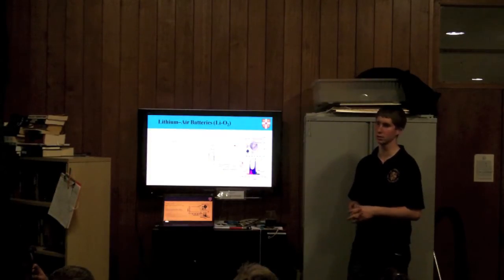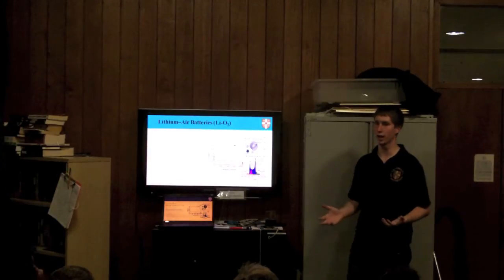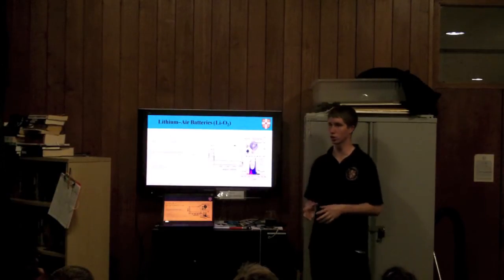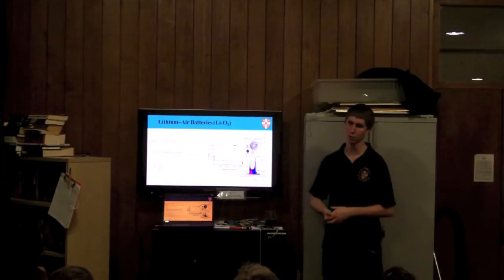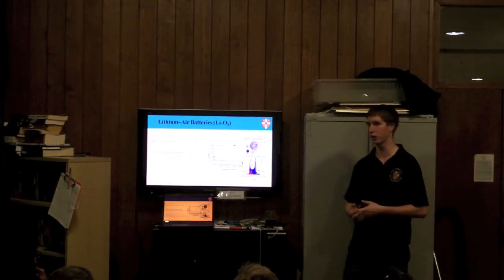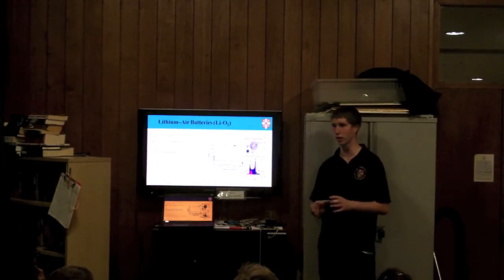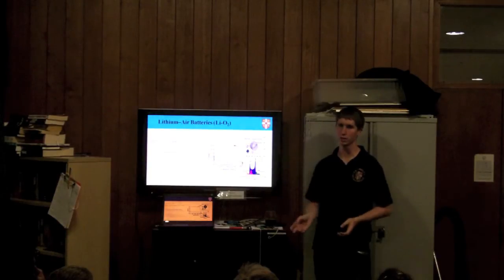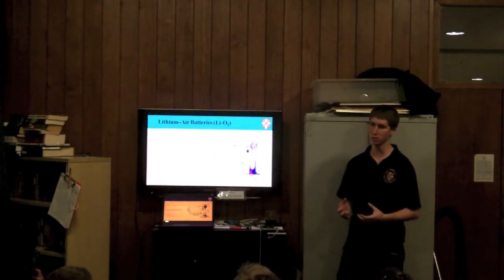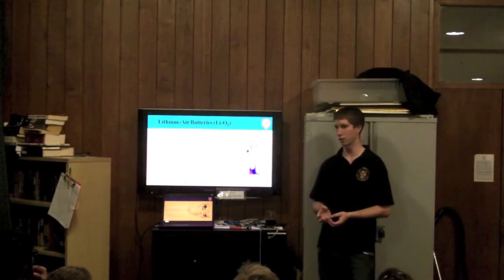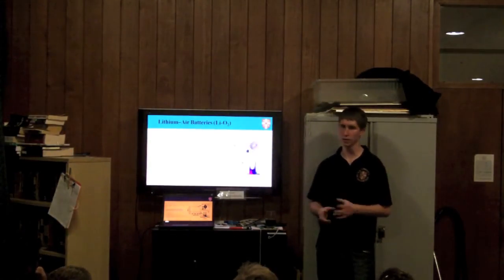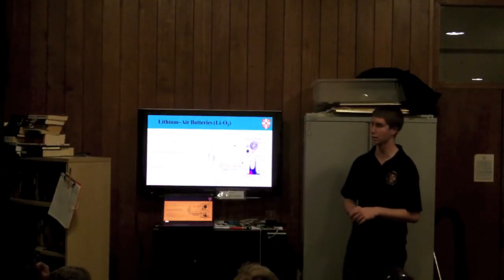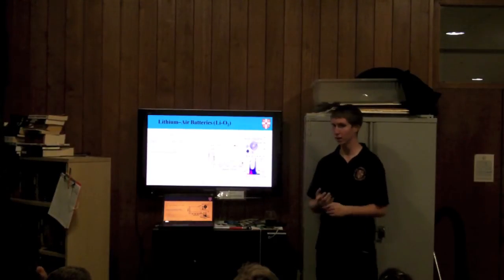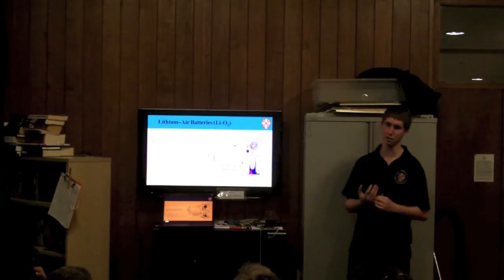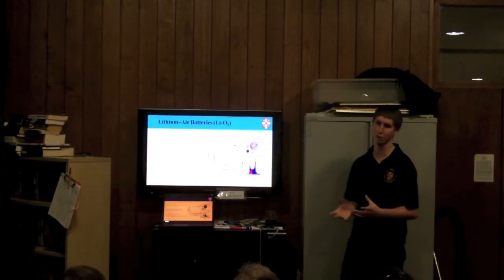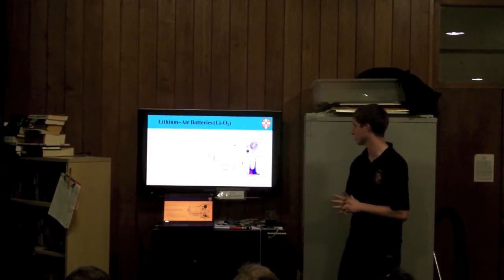One of the reasons is, and especially in this system, other reactions happen. Things besides the ones that you're shown of what should happen, happen. And so these generally degrade the system. So in the battery you have now, it might be things with the electrolyte react and they form these surface coatings. With the Lithium-air system, it's basically similar things. The electrode that it's on just gets clogged up with all these side products. And so you have to limit the side chemistry from happening. If you use real air, that's why they would stop working so much faster, because real air would have that many more side reactions that happen. And there's already ones going on.